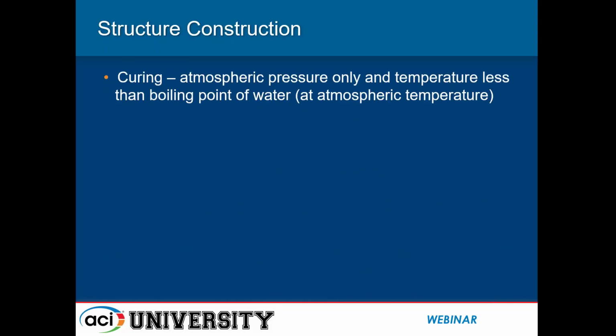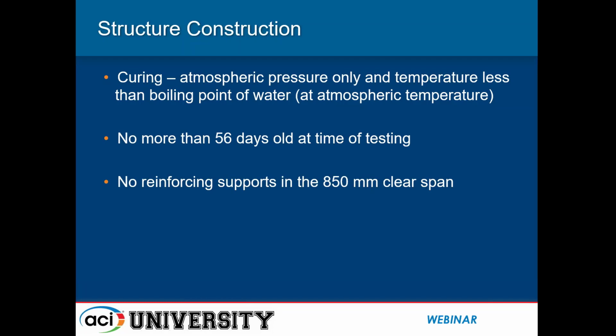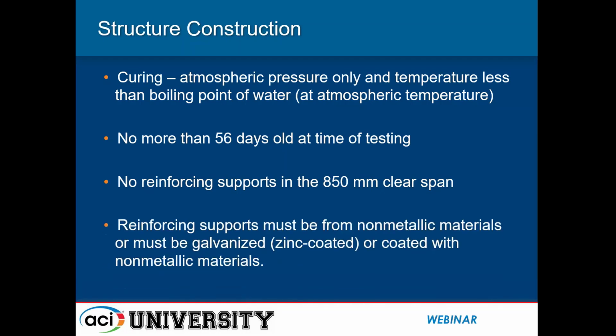For the structure construction, curing must be at atmospheric pressure only, and the temperature must be less than the boiling point of water at the atmospheric temperature. The structure itself or the member itself must be no more than 56 days old at the time of testing. And no reinforcing supports may be provided in the 850 millimeter clear span. The reinforcing support must be within the ends of the member. Reinforcing supports must be made from non-metallic materials, or metallic materials must be galvanized or zinc coated, or coated with non-metallic materials.